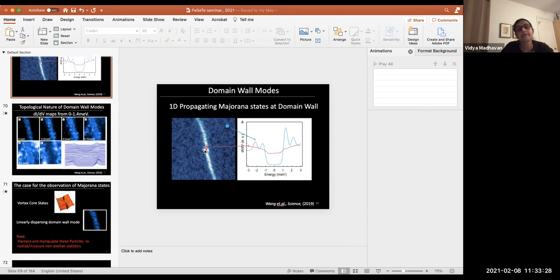Okay. I guess that's one reason why I asked about alloy disorder, because you could, for example, think of the case where you would have regions of your crystal that are not exactly that 40% stoichiometry, in which case you may not have the topological surface state at 1.8 meV, right? So at the boundary to such a region, I guess it's maybe hard to find them, but the problem is, that's a really good question, actually.